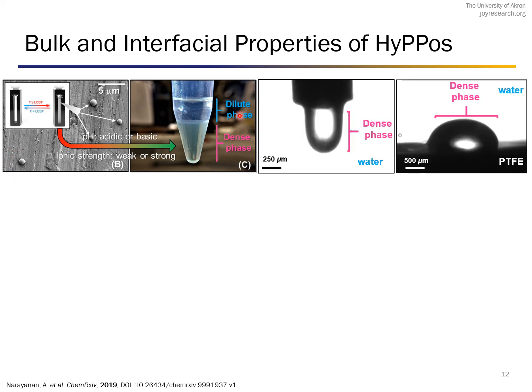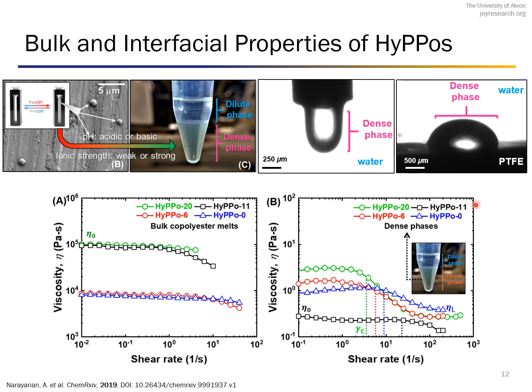The interesting properties of these dense phases are several, among which low interfacial tension, as you can see from this image, is a very unique property. At the same time, these HyPPos, or hybrid protein-like polyesters, show higher contact angle on hydrophobic surfaces in underwater conditions, which helps to spread these adhesives in underwater conditions without sticking onto the pipette tips.